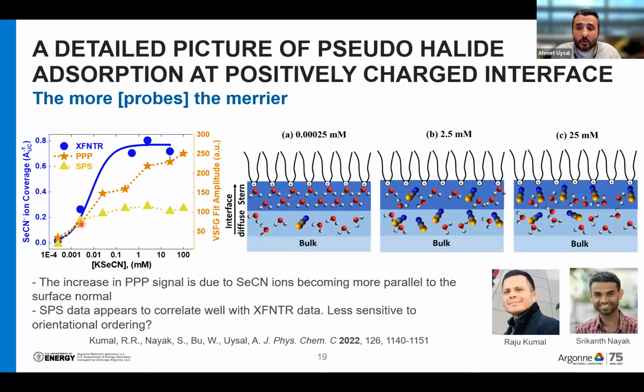Now one interesting observation here is that this SPS polarization combination looks like it is following the fluorescence signal. So it seems like the SPS is less sensitive to the orientational ordering changes that we observe in the system, and it is pretty much correlating with the number density. This is just an observation. We're still trying to develop a better understanding of why it is happening in this way.